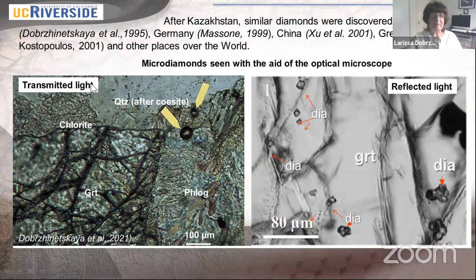So this, for example, is an optical microscope image, transmitted light, a regular, transparent petrographic thin section, 30 micron thickness. You see here garnet, transmitted light, crossed nicols. You see here the garnet, okay? You see here phlogopite, and you see here chlorite. And quartz, which we now know was after coesite, a high pressure polymorph of quartz.